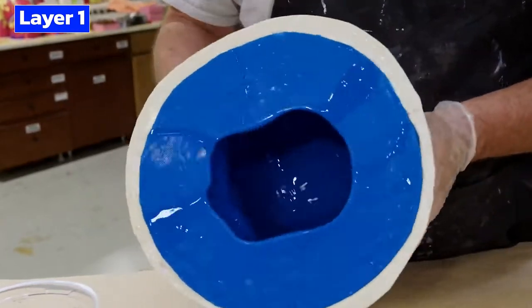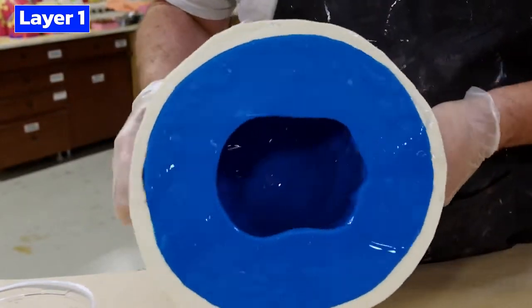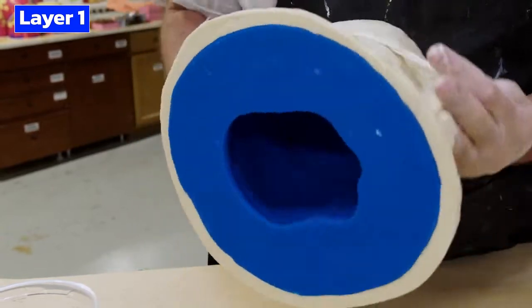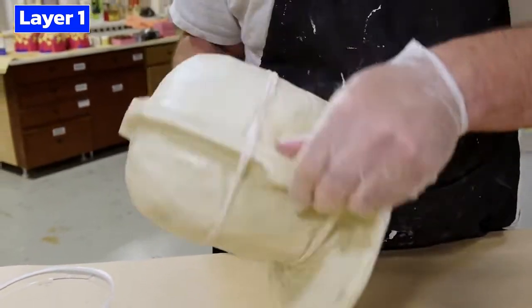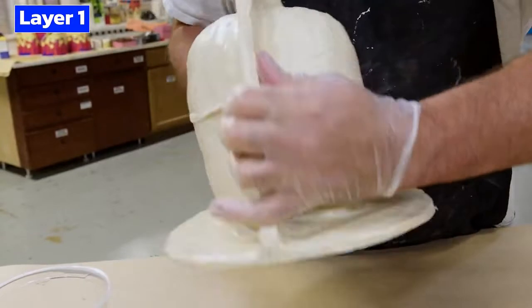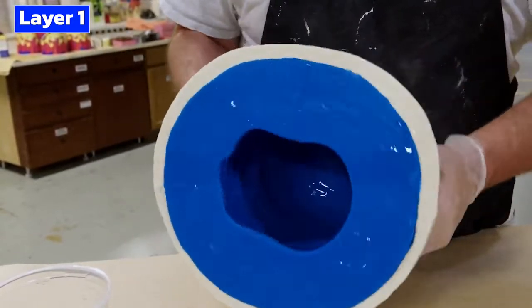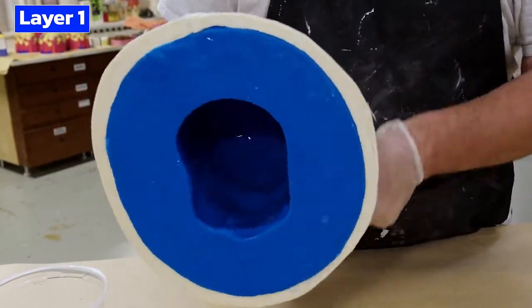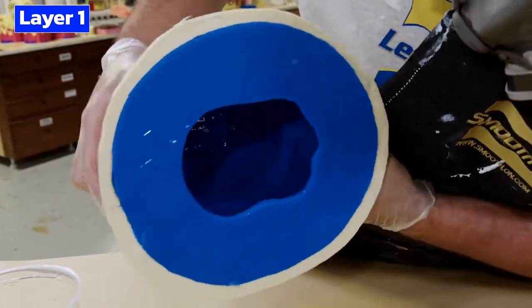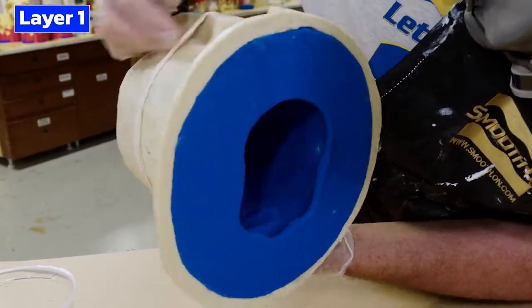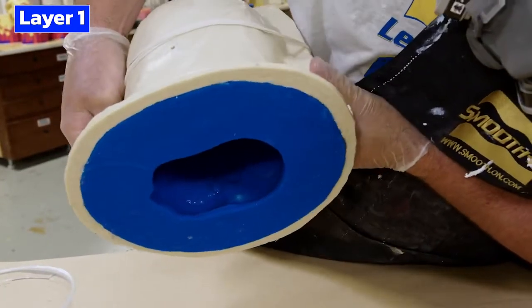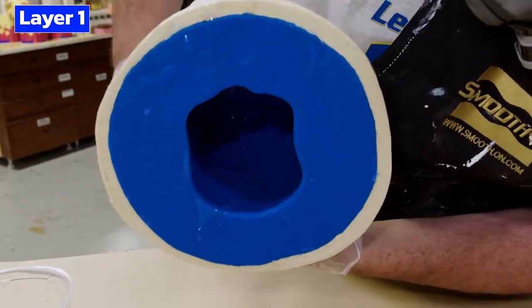I find that the biggest secret to rotational casting is that you're gonna do it in a few layers. So you're going to apply a couple of different batches, and the batch should be just as much material to cover the inside, but not have too much that is just slumping in the mold constantly.